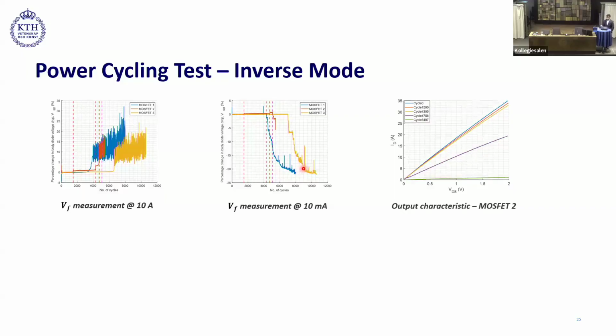We did some output characteristics test. Here we see that the on-state resistance increases with cycling. And in this cycle number, which is 4756, this measurement is done after the device has failed. And we see that it showed a very high RDS on. And then at the end of the test, when we have also observed this reduction in this voltage drop at low current, we see that RDS on has become quite high.